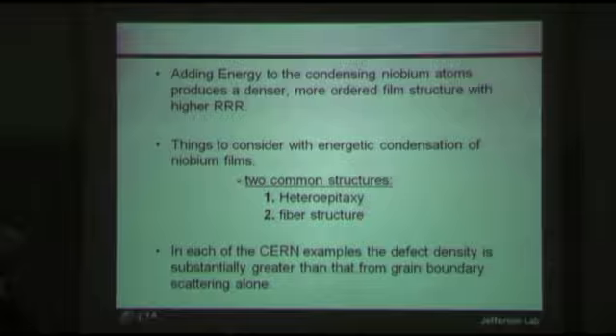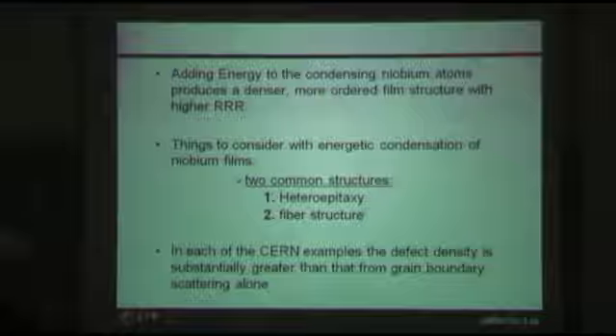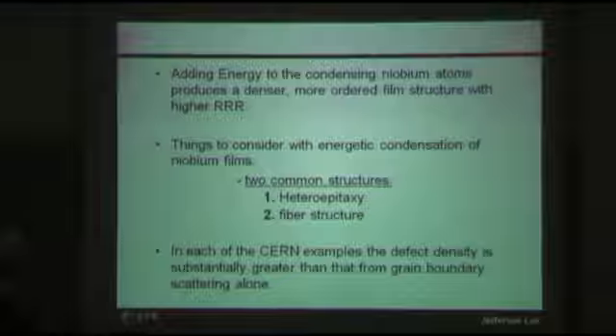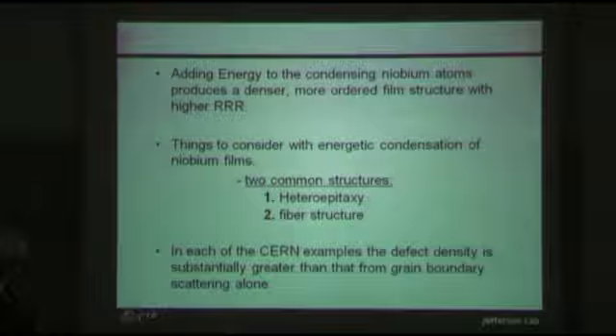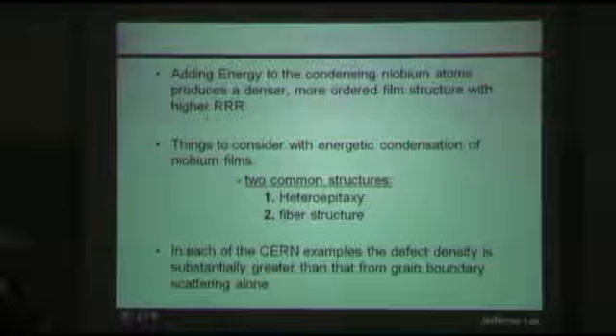This is called ion stitching. It's nothing new. Andre and his collaborators have done this many times at Berkeley. And the potential advantage of this is that it will support much thicker films. Shear stress builds up as the film gets thicker, and peeling won't be a problem with the thicker films. This might be very useful if the defect density doesn't saturate with increasing film thickness. So by the time you reach the RF surface, you can even achieve a better RRR.